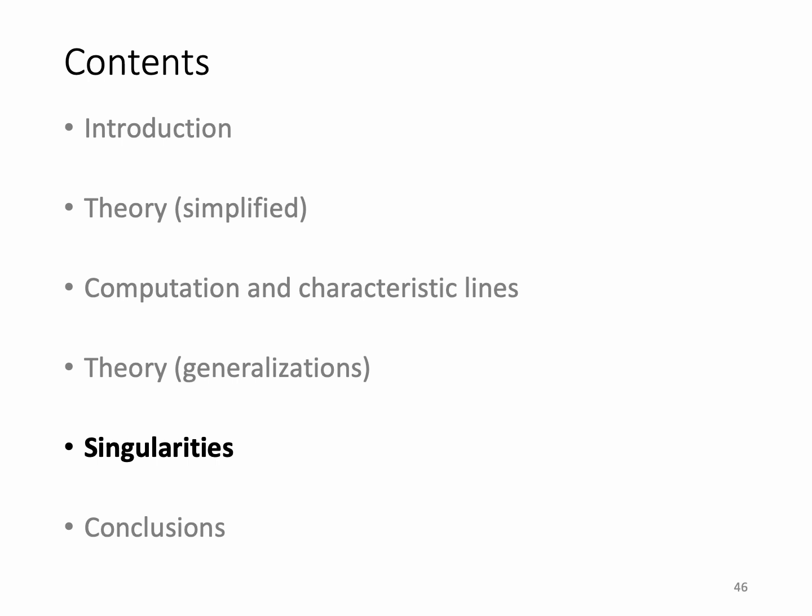So you may have noticed there was a bit of a hole in everything I've been saying, and that is we've assumed that the stress and, say, for example, the elastic strain have unique eigenvectors. However, when the eigenvalues repeat, they will actually have non-unique eigenvectors, and this manifests as singularities. So, for example, the identity matrix has two eigenvalues of 1, and any vector is an eigenvector.